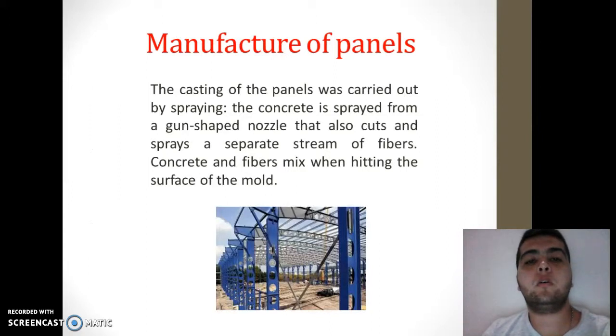For the manufacturing of the panels, commercial panels were made with 50 kilograms of Portland cement, 50 kilograms of sand, and 16 to 18 liters of water were taken into account. Casting of the panels was carried out by spraying, where the concrete is sprayed. The panels obtained were demolded after 24 hours and cured inside the factory at room temperature.